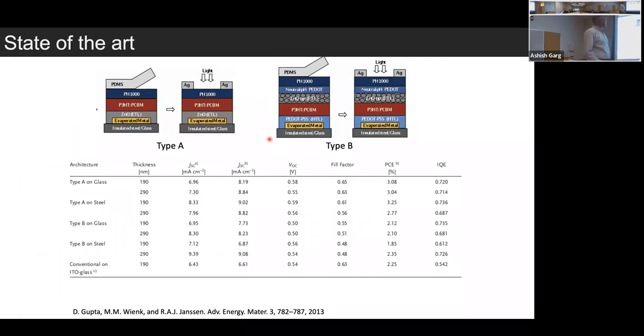And also they used layers where you can have either an inverted configuration, where zinc oxide is put at the bottom, or you can have a normal configuration where you have PEDOT:PSS, which is a hole transport layer. So zinc oxide is an N-type oxide, so you can use it as an N-type layer, which means electrons will move to the bottom, or you can put PEDOT:PSS, which is a P-type material, so that holes will move towards the bottom. So type A is the inverted architecture, type B is the normal architecture. Literature has shown that by using different polymers, one can achieve efficiencies of the order of about 2 to 3%.